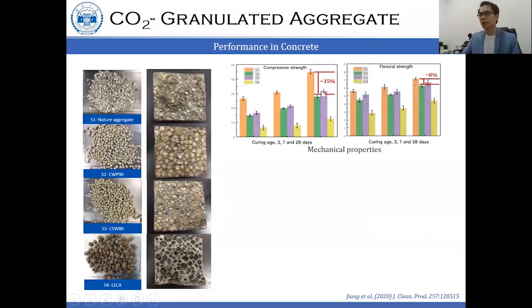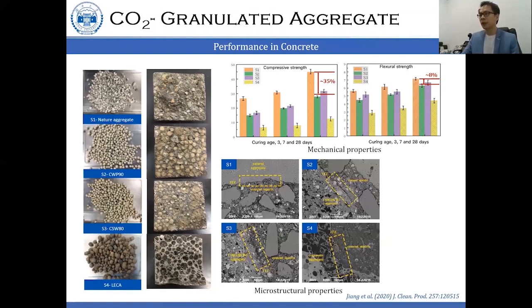So we replace 100% of the coarse aggregate, both natural and commercial lightweight aggregates. And we can maintain the strength at 28 days at 30 megapascal. However, for the commercial lightweight aggregate, it only can attain 10 megapascal. And if you compare the compressive strength with the flexural strength, the reduction for the flexural strength is much lower. And we are expecting the aggregate we produce will have a better bonding between the aggregate and new cement paste to compensate the low strength of the aggregate.